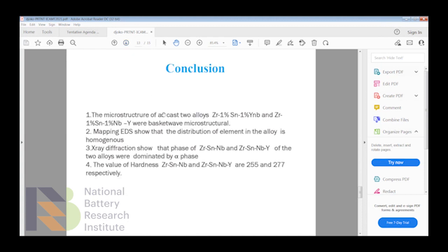Conclusion: the microstructure of the alloys Zr 1% Sn 1% Nb, and Zr 1% Sn 1% Nb with yttrium, is basket-weave microstructure. EDS mapping shows the element distribution of the alloys is homogeneous. X-ray diffraction shows that the phases of the two alloys are dominated by alpha phase and minor beta phase. The hardness values of zirconium stannum niobium and zirconium stannum niobium yttrium are 255 and 277 respectively.